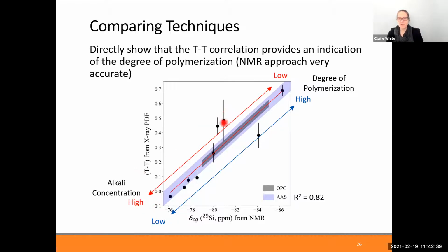So what we really want to do is be within the upper right-hand corner of this plot when making the gels, because a more polymerized gel is likely to degrade at a slower rate compared to a less polymerized gel if everything else tends to be the same. And one thing I should say here is that for Portland cement, this is the range that you get for the degree of polymerization. If you look at alkali-activated concretes, we really span a very wide range. So it's important to get a sense of the degree of polymerization of the gels, because if you're down here, this might be an issue when it comes to long-term performance.